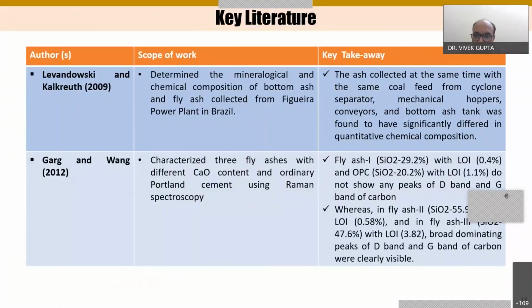These are the different key literatures you can see. In 2009, Lewandowski determined the mineralogical and chemical composition of the bottom ash and the fly ash collected from Figueira power plant in Brazil. What they observed is that the ash collected at the same time with the same coal feed from the cyclone separator, mechanical hoppers, conveyors, and the bottom ash tank, these being four different equipment or process stages from which we can collect the ash from the industry, was found to differ significantly in quantitative chemical composition. So from this we can see how dynamic they are. We have the same coal feed and the ash collected at the same time, still we are getting different chemical composition.